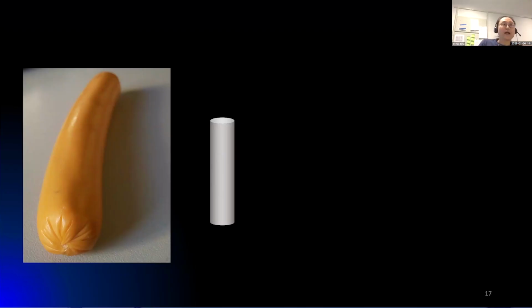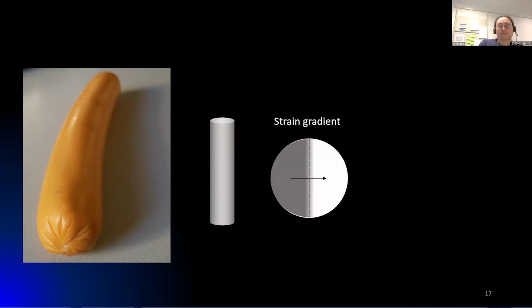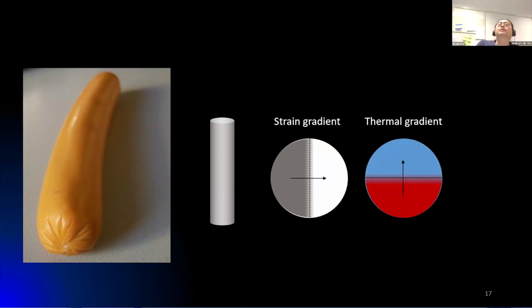But if we bend the sausage by our hand, what this means, if you see the cross section, is that you are inducing a strain gradient. You are stretching the outer surface out, but compressing the inner surface down a little bit. And there's a strain gradient across the cross section. So what happens if you put it on the pan to cook it? There's a gradient given by the heat. There's a thermal gradient. So the heat will expand the material because of the thermal expansion.